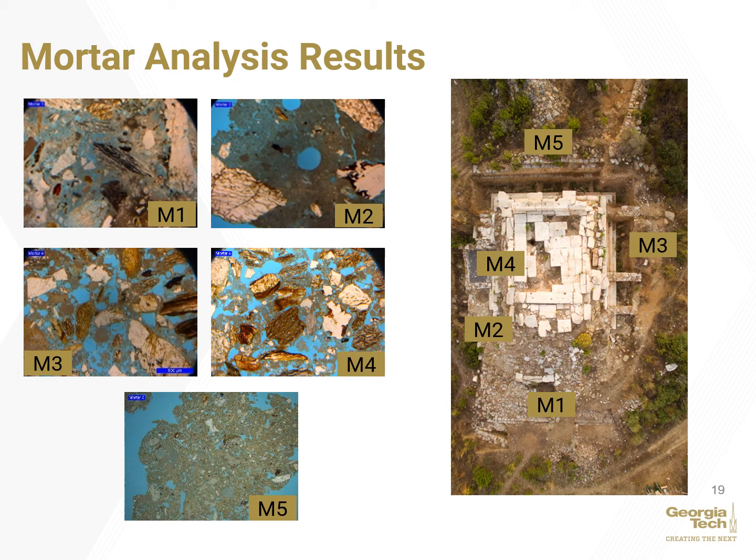And this can be the reason why we see deterioration of mortars in relation to the overall weathering and accumulation of water around the temple. So M3 and M4 specifically show abundant amount of void space, and those are the mortar and plaster samples from the Byzantine walls. The difference between void volumes may be related to placement techniques in addition to variations in initial water to solid ratio of the fresh material.